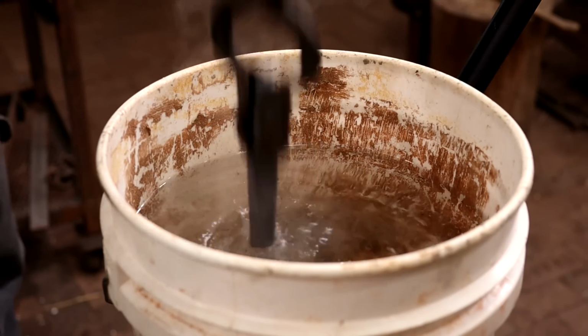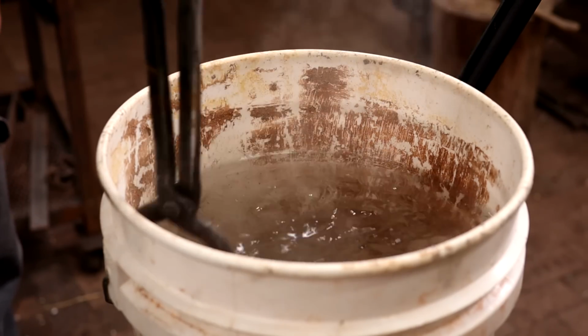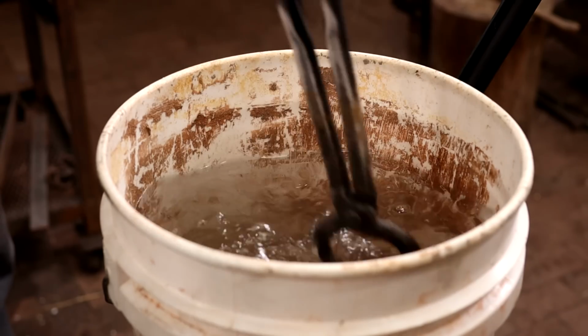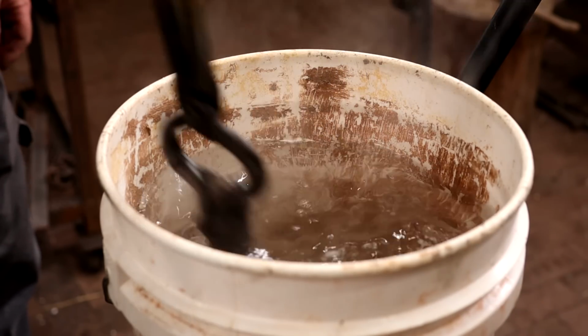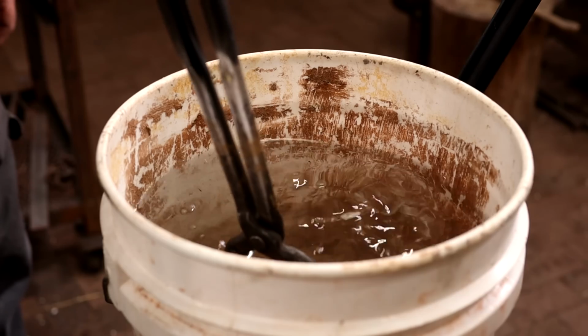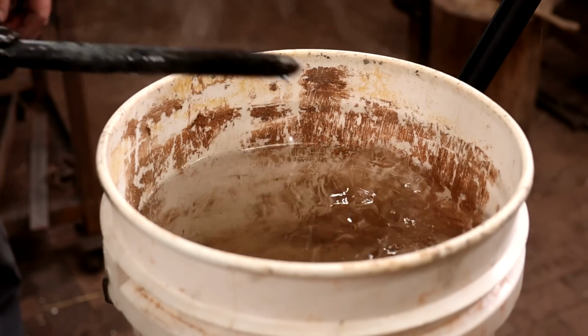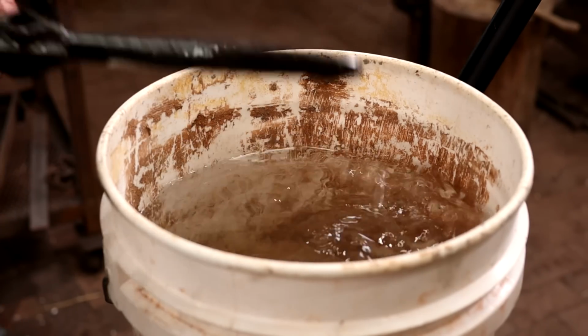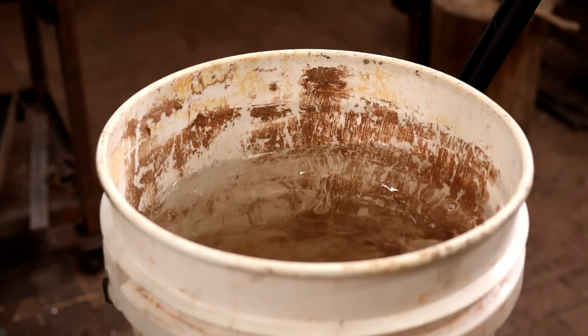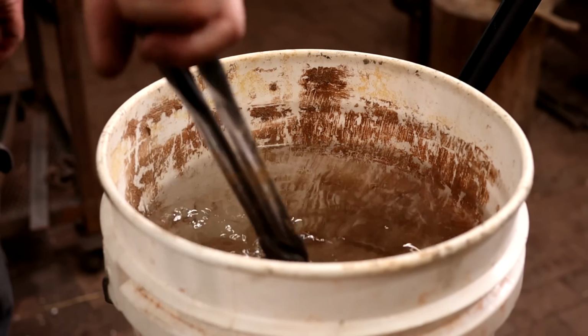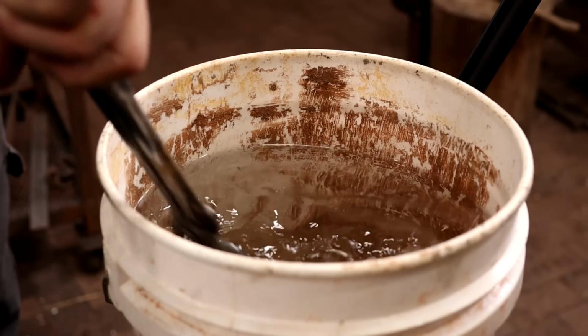Then when you quench, try to move them up and down and around in a figure eight so that they quench very evenly. If you don't move it, air bubbles form on one side or the other, and then you get a real uneven quench, and that can contribute to warping. Although be careful if you're doing something thin, moving it side to side can also contribute to warping. So in that case, just vertically might be the best option.